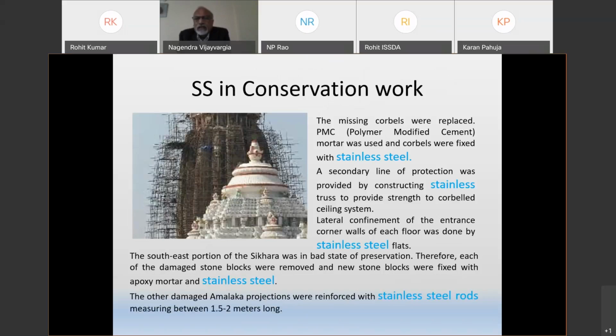How have they conserved it? I am not a civil engineer, so don't ask me the civil aspect of this, but on the stainless steel aspect, you can definitely ask. The missing corbels were replaced by polymer modified cement, and these were fixed by stainless steel. A secondary line of protection was provided by constructing a stainless steel truss to provide strength to the corbelled ceiling system. Corner walls of each floor were done with stainless steel flats. The southeast portion of the structure was in bad shape. Therefore, each of the damaged stone blocks was removed and new stone blocks were fixed with epoxy mortar and stainless steel. And of course, the Amalaka projections were reinforced with stainless steel rods.